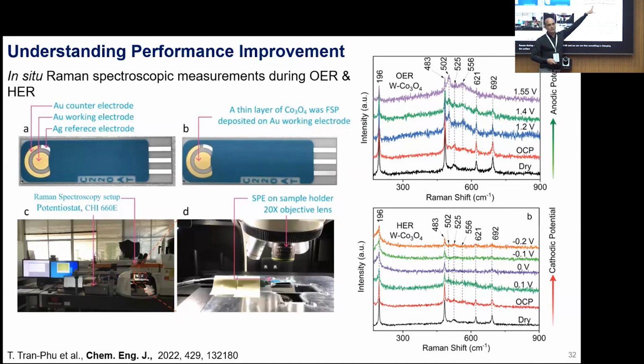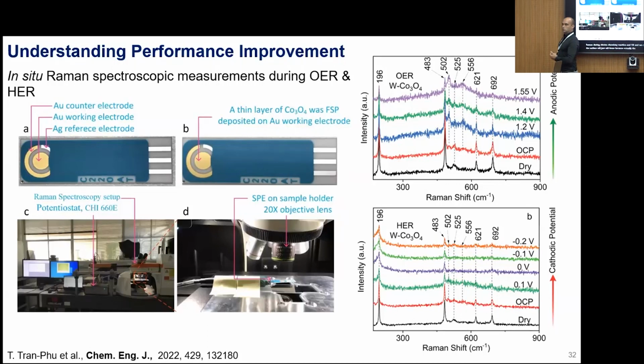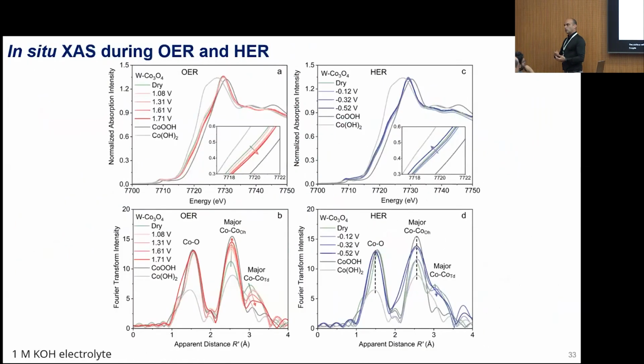Well, that's well known, because actually the cobalt oxide produces cobalt oxyhydroxide and cobalt hydroxide during OER and HER reaction. We went to the synchrotron to perform in situ study. We confirmed this, so this surface is basically the same, and they are not the original cobalt oxide. So there is no tungsten interfering.